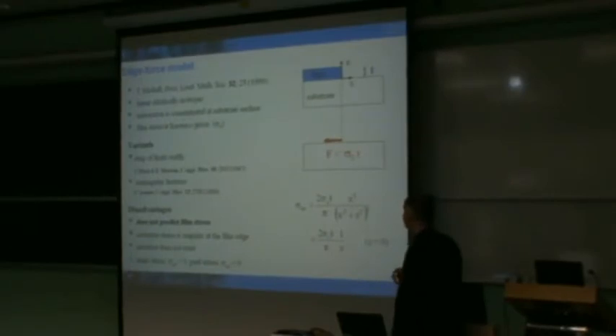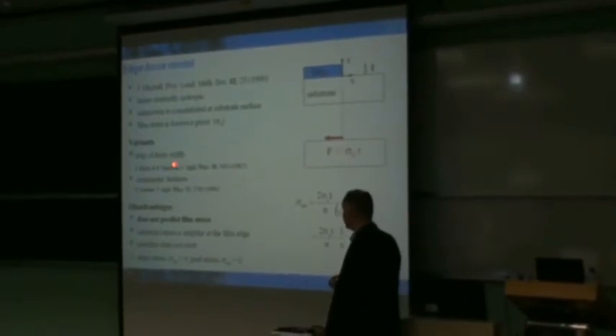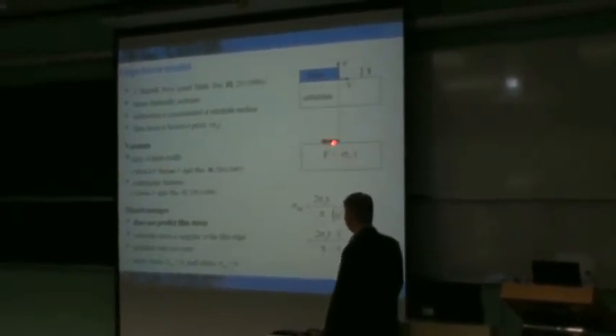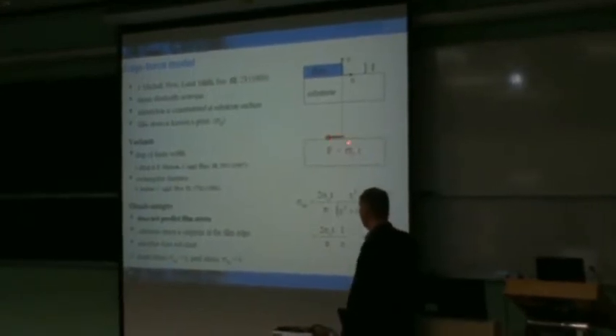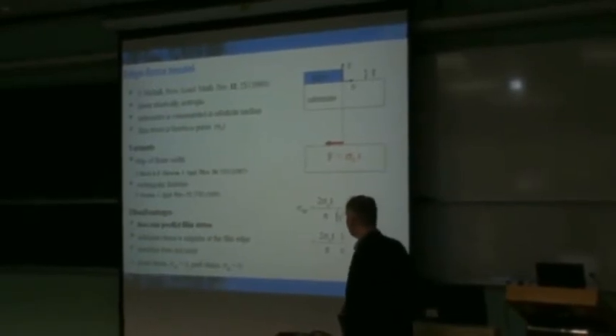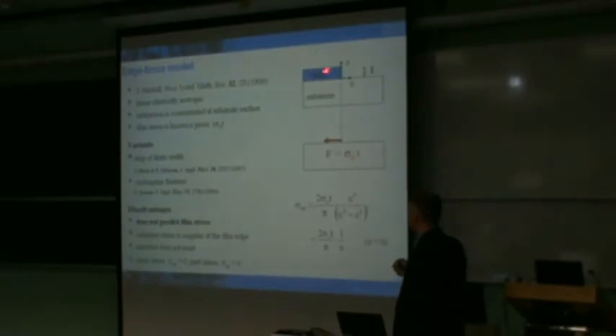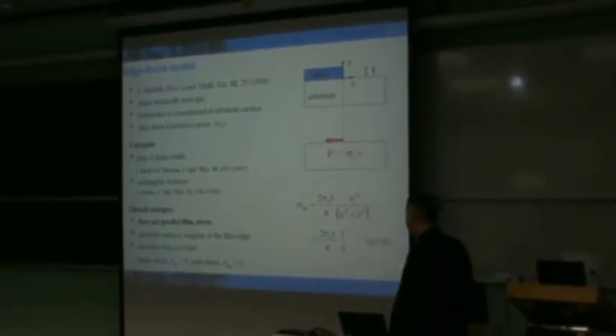There are various ways in which this has been implemented. One that was implemented in the 60s was to consider not just one edge, but two edges, similar to the strained silicon device that I showed earlier. The other aspect is to not stick with only a plane strain condition, but you can actually take the idea of taking these forces and placing them in arbitrary positions within the structure, such as one that has rectangular or other types of features, even circular features, that exist on some of the substrate. So the transition to three dimensions is quite applicable in this technique. The problem, of course, is that we have no real prediction of what's going on in the film in this approach. It only considers the effect of the film within the substrate region, but perhaps that's okay. It again depends on the application that you're looking at.